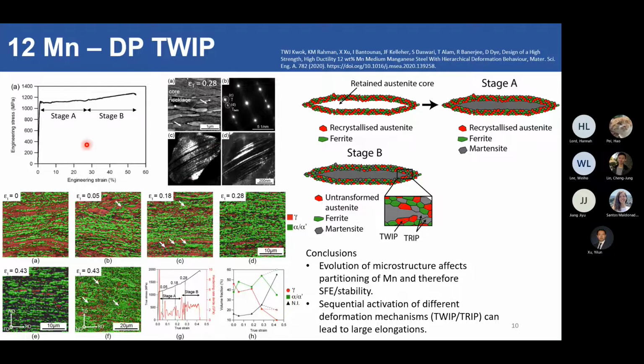And once all of the core austenite grains have transformed, then the load is partitioned into the necklace grains, which then start to deform. And because your necklace grains were more enriched in manganese, some of them actually are able to twin, as you can see from this particular grain here. Very nice twins in there. So what this tells us at the end of the day is that the evolution of microstructure actually affects the partitioning of manganese, which then affects things like austenite stability and stacking fault energy.